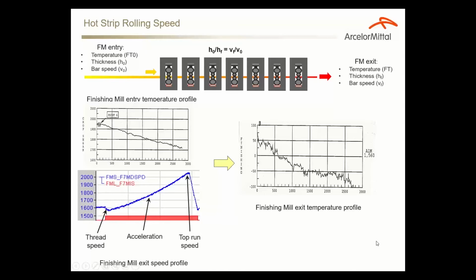Important parameters for the mill is to set up the rolling speed. Here, a very important feature is what we call mass flow constancy. The mass traveling through the mill is constant, so because the width is kept constant in this kind of rolling, the entry thickness to exit thickness ratio is exactly the ratio of the speed the strip exits from the mill to the speed the strip enters the mill.